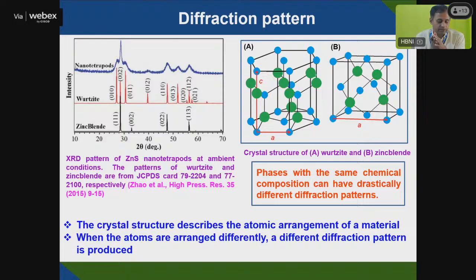If you see the common diffraction pattern, I have shown here the XRD pattern of zinc sulfide that exists in the wurtzite structure, the hexagonal, or the zinc blende structure, or a nano tetrapod structure. You can see that in zinc blende, you are getting the 111 and 002 planes. But in wurtzite, you have a set of three planes, 010, 002, and 011. But in the case of a nano tetrapod, you are getting broad peaks. So you can easily identify whether the crystal structure is wurtzite or zinc blende from the crystal planes. This kind of identification can be done with the help of X-ray diffraction patterns.